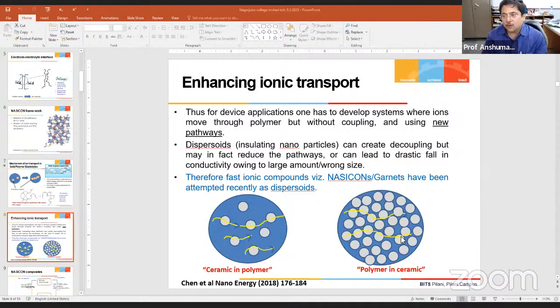Right. So now you have new materials where ceramic particles inside can also support the ionic transport, either by the polymer-ceramic interface or by providing pathways through their own grains. Now a lot of mechanisms are being thought about, how the ionic transport is happening, whether through the grains of the ceramics or through the polymer-ceramic interface. You can put polymer in ceramic, you can put ceramic in polymer and make a huge compositional variation range now. And since they are developed, the conductivity has reached a very high value. And this high value of conductivity is about 10 to the power -4 in sodium as well as lithium systems.